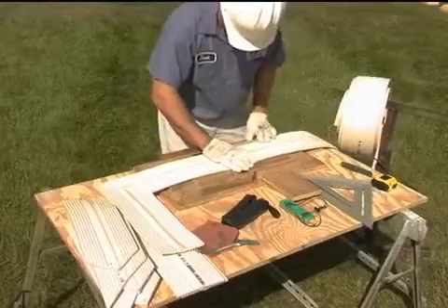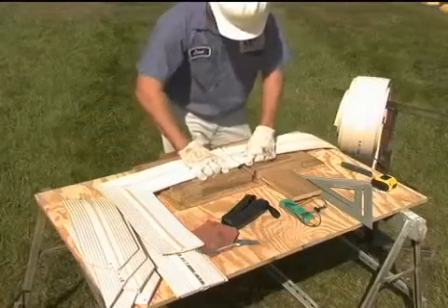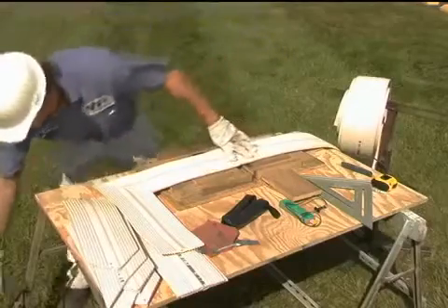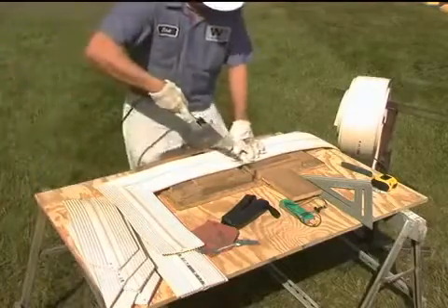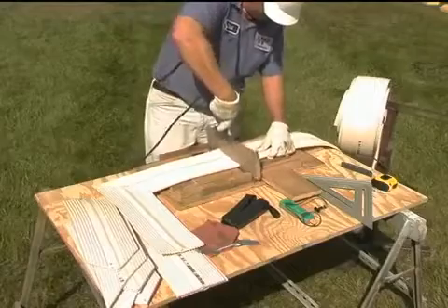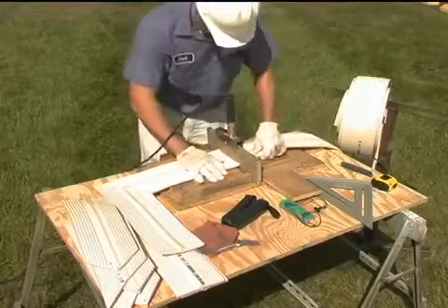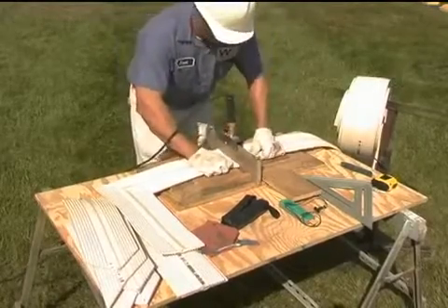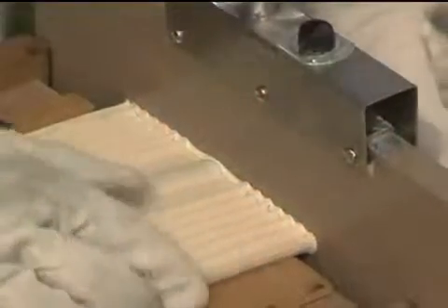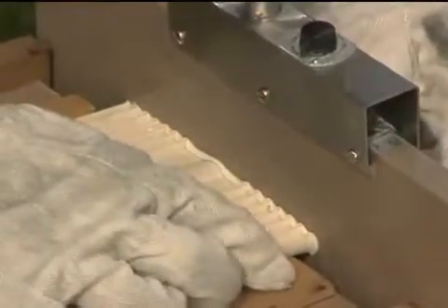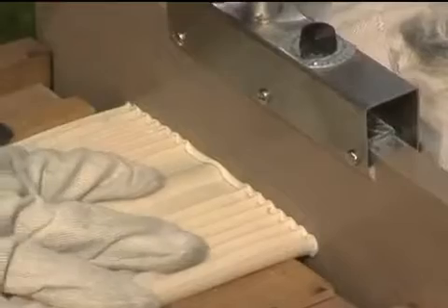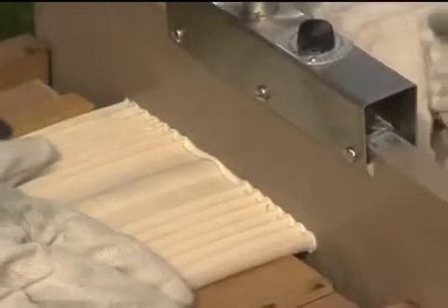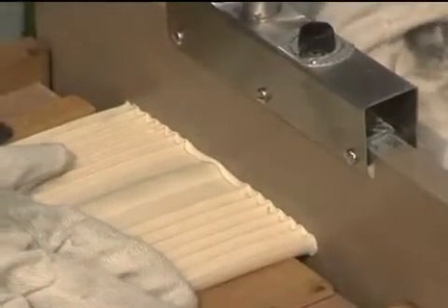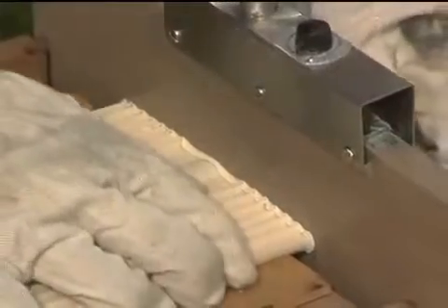When butt welding 2 straight lengths of water stop, you must melt the adjoining pieces simultaneously. Melted PVC cools very quickly, and working time is limited to a few seconds before the material returns to a solid, preventing a proper bond. When melting the water stop, you want no less than a 1/8 inch melted bead of PVC around the entire perimeter of the water stop at the interface with the welding iron. This ensures that you will have a good bond throughout the entire width and thickness of the water stop.